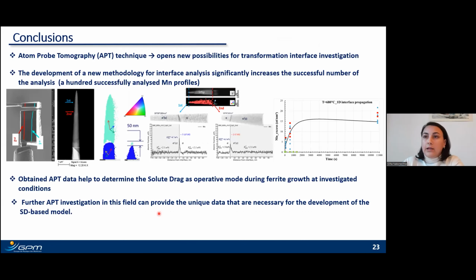I would like to conclude that thanks to the atom probe technique, we obtain unique data, and we also developed a new methodology for interface analysis, with which we significantly increased the number of successful runs. More than 100 interfaces were successfully analyzed. This APT data helped to determine that solute drag is the operating mode during ferrite growth at the investigated conditions. But what is more important is that further APT investigation in this field can provide very important parameters for the development of solute drag-based models, which are very promising.